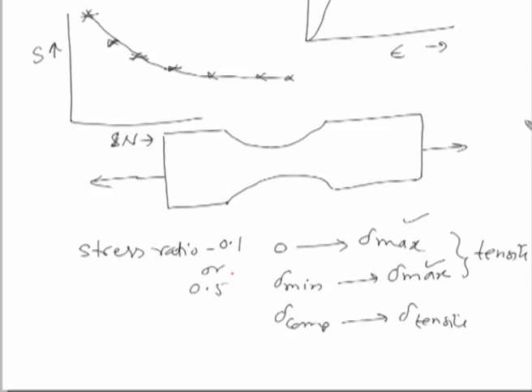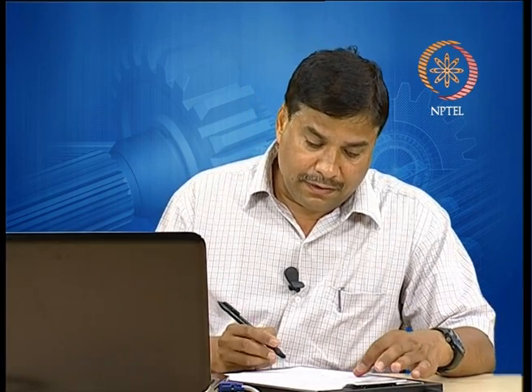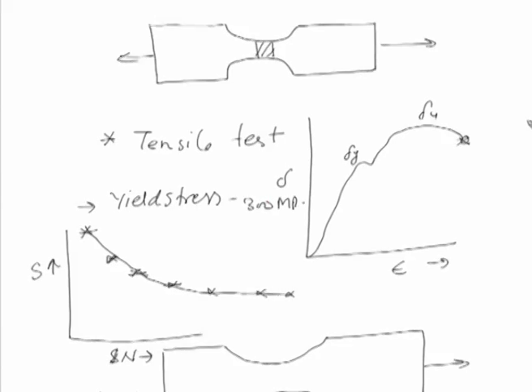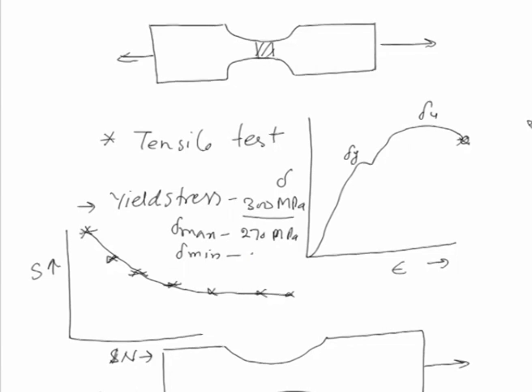So, if you are taking a stress ratio of 0.1, it indicates that the maximum stress will be about 10 times the minimum stress. Say the yield strength comes out to be 300 MPa, then to start with, sigma max we can take as 270 MPa, and sigma minimum, when using the stress ratio, will be 27 MPa. This is how it can be done.